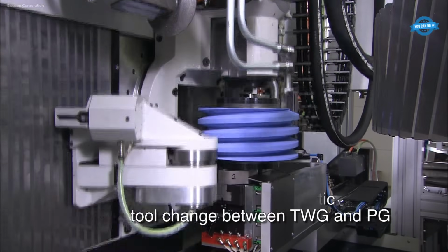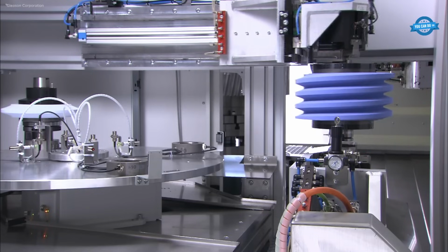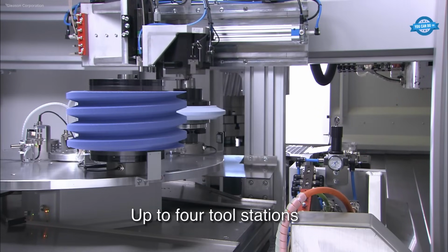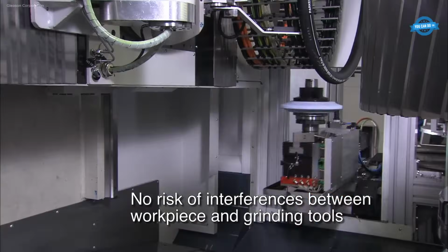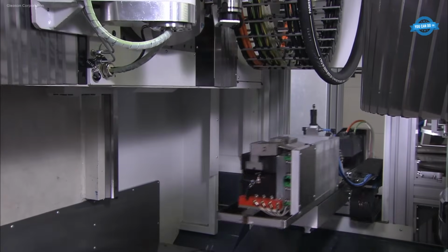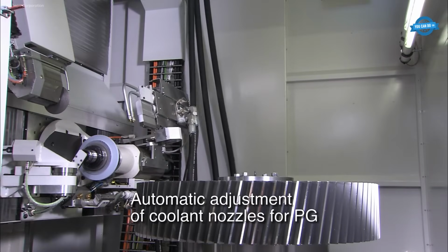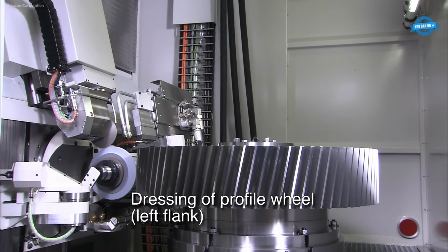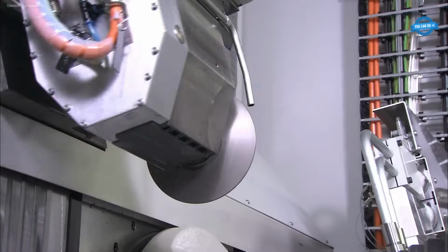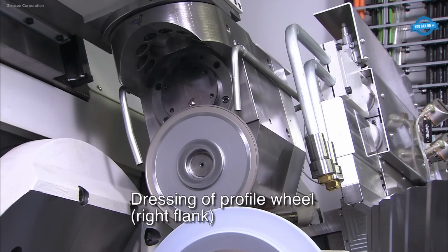Roughing then begins using a coarse grit threaded wheel to achieve high material removal rates. A gear with module 14, 84 teeth, 255 mm face width, and an 11 degrees helix angle is ground, achieving 36% time savings over conventional profile grinding.